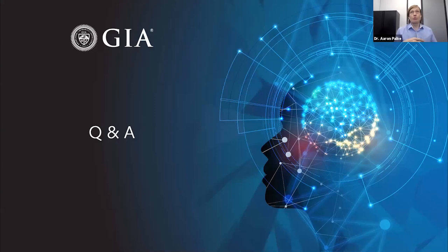Now, we corroborate those calls with information from trace element chemistry and spectroscopy. So we look for cobalt concentrations, and we also look for the relative concentrations of cobalt and iron in these stones. And we look at the spectroscopy as well. The iron has its own unique spectral contribution to the absorption spectrum, and so you look at the relative contributions of iron and cobalt in the absorption spectrum. And then we take all these 3 pieces of evidence together in order to make these separations between cobalt spinel